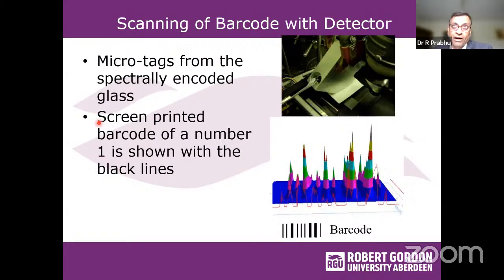Again, our objective was to make an invisible spectral code that can be embedded into a currency note. So we used a screen printing method to demonstrate this spectral integration approach. We embedded spectral codes inside the paper as well as on top of the paper. This is a typical paper we made by screen printing. And this was the barcode we printed. And you can see the output from a specially made detector specific to this europium tag. You can see it has strong signals and very nearly zero background. So this provides a good signal to noise ratio for the detection system.